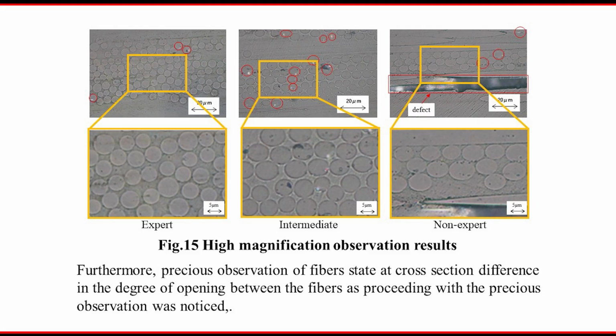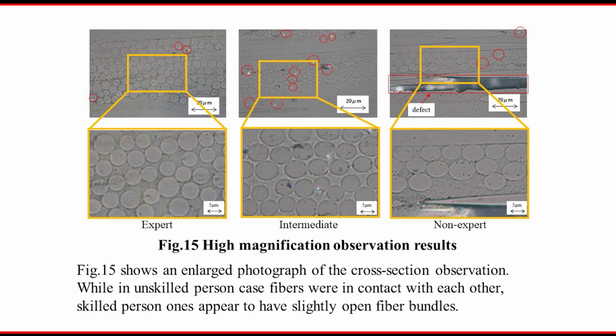If the filaments exist in the matrix individually, that is the opening state. So we noticed that the opening state is different. This figure shows an enlarged photograph of the cross-sectional observation. In the unskilled person's case, the fibers were in contact with each other. In the unskilled person, you can see the filaments contacting each other, while the skilled person apparently has a slightly open fiber bundle. The intermediate person has a little bit of opening.